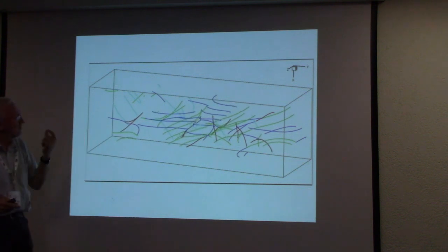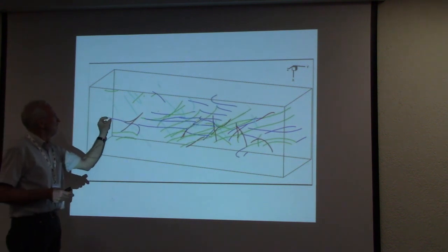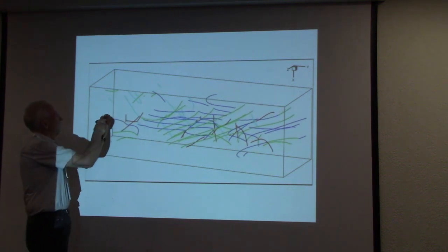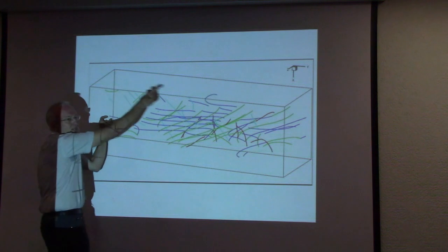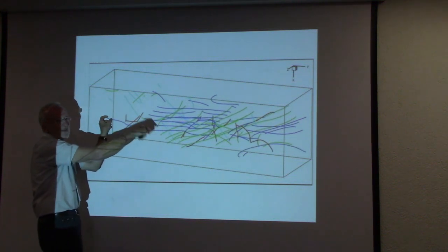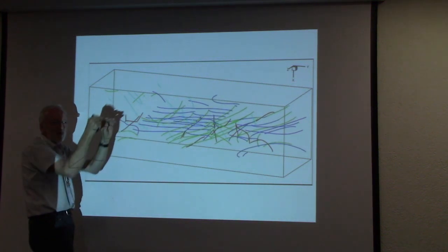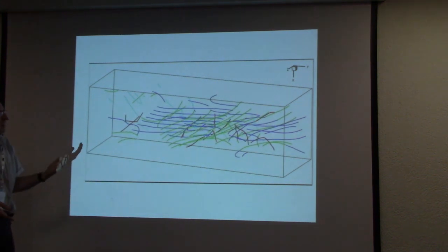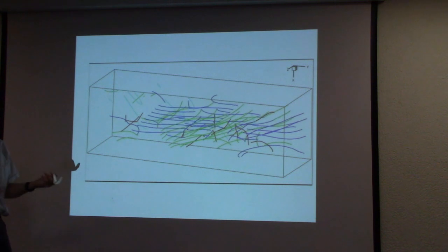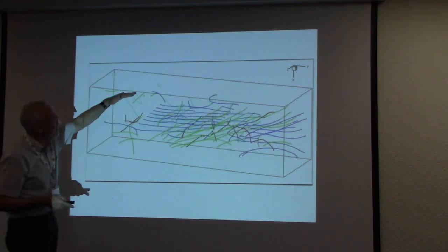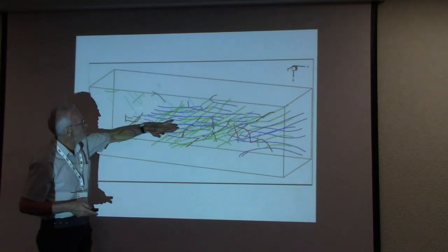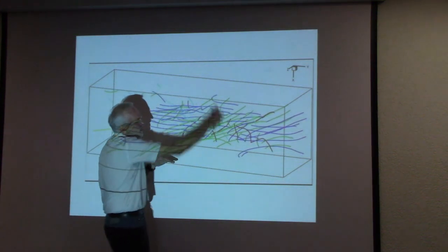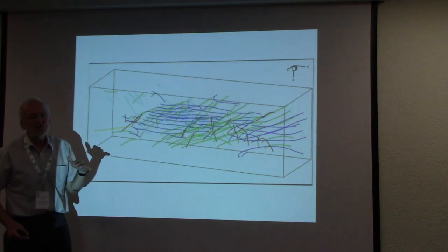When you make this 3D calculation, you have to take all small parts of this and look at the effect of these small parts on all the other dislocations. Yes? And you have to do this for every movement step. That makes the limitation for this discrete dislocation simulation. What you really can see is that all the dislocations are stored here in the center and piled up to this neutral axis.